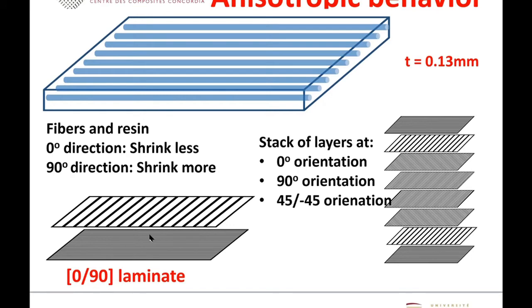Now what happens in this case is that you have the layer at the bottom along the 0 degree orientation. When you heat or cool it, it expands and contracts very little because the fiber is stiff, but it expands and contracts a lot along this transverse direction.